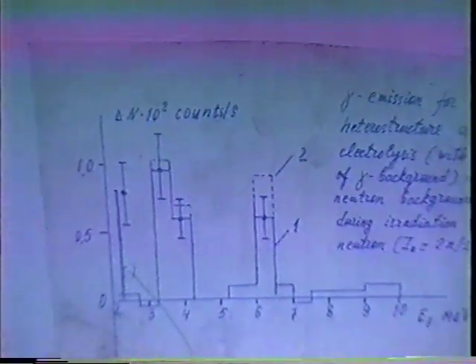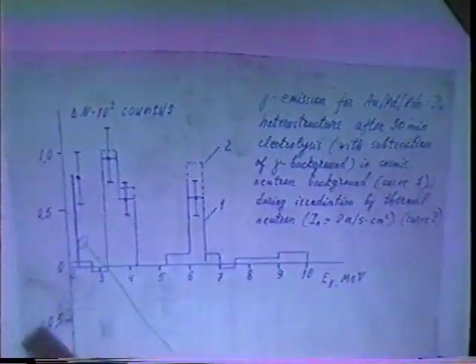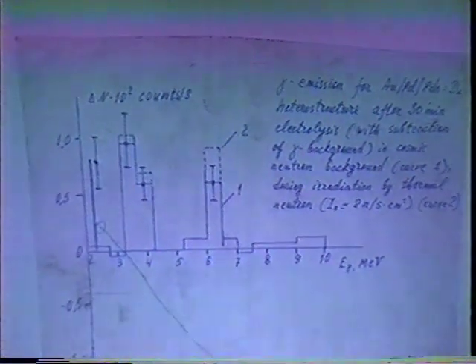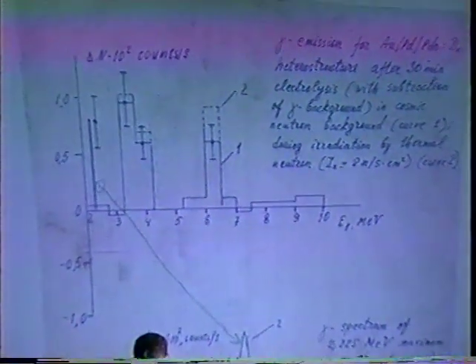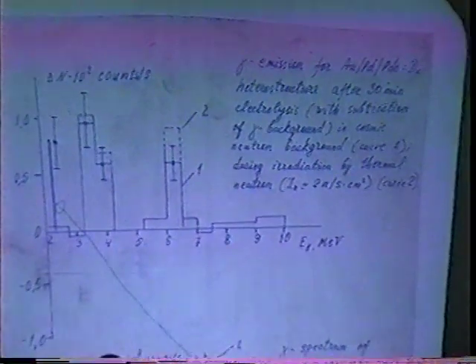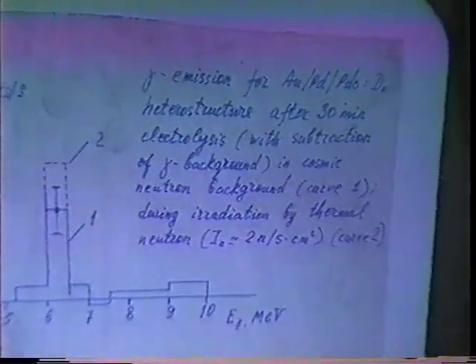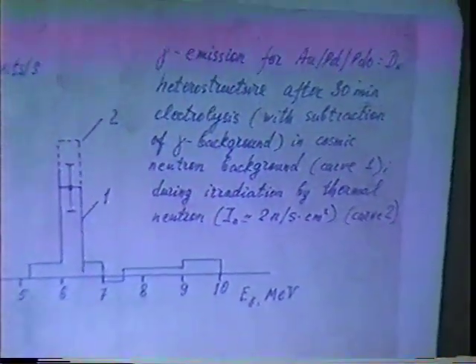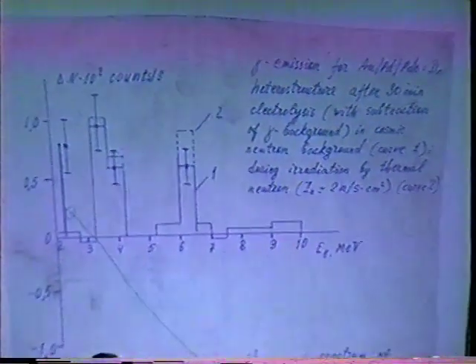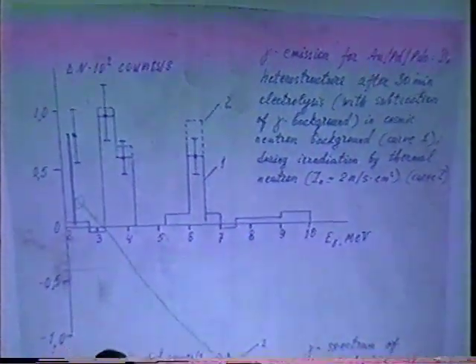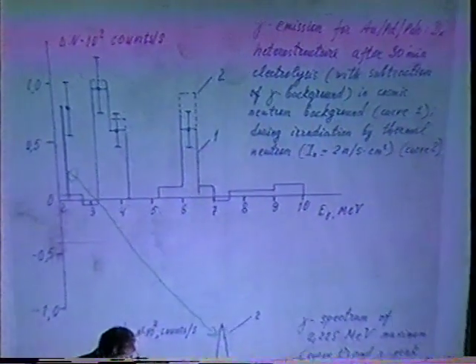And here are the results with gamma emission, and they observed 3 peaks, and 1 peak corresponds to the well-known peak of 2.2 MeV energy, and 2 other peaks at larger energy. Probably they correspond to other possible reactions.